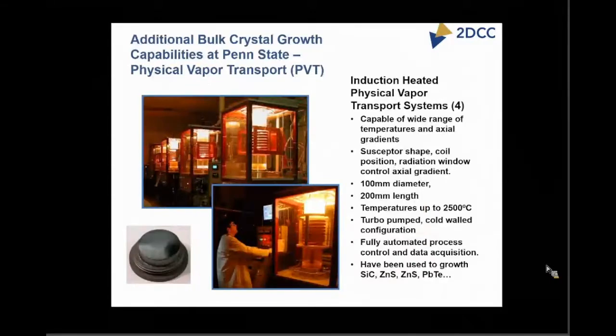And there are currently 4 of these systems available for use, depending on the materials of interest, in support of the 2DCC on a limited basis. So we have a wide temperature range and a wide range of axial gradients. You can control transport in the furnace by the susceptor shape, because these are induction heated furnaces, the susceptor material, the coil position, and radiation windows. And so you have a very wide range of flexibility in terms of the transport.